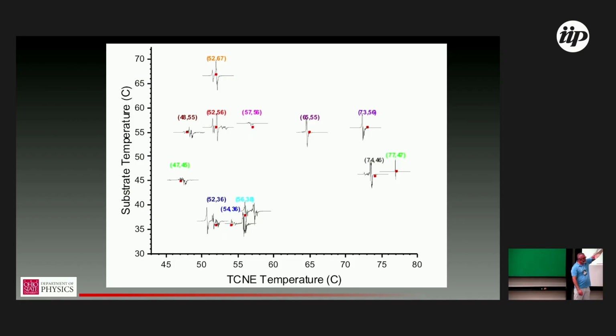But you can just sort of see the peak structure, right? You can play a little bit of Where's Waldo for a moment and see where you want to grow. You want to grow way out here at the edge of phase space. For good crystal growth, generally there's a rule of thumb that you want to grow just colder than the decomposition temperature of the material. You want to give enough thermal energy for your constituents to move around and find their true equilibrium, not some metastable configuration that's going to give you defects. So you really want to be at the edge of the growth window.